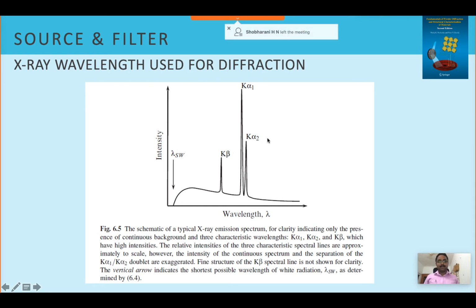Still we have K alpha 1 and K alpha 2. So here we should be very careful. Few instruments give directly K alpha only, that is, it is an average. Then few instruments directly give a ratio of K alpha 1 and K alpha 2, K alpha 1 by K alpha 2. So in that way we should be very careful with the terminology. If we have a ratio, it will always be 0.5. You can see the intensity of K alpha 2 is half the intensity of K alpha 1, so it is 0.5. K beta will be removed.